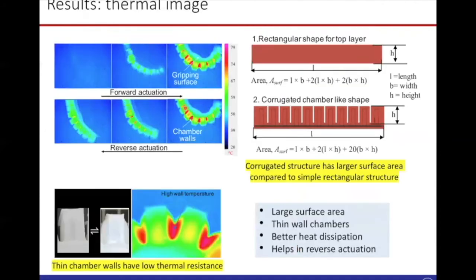Now let's look at the thermal image of this actuator in the forward actuation and in the reverse actuation. You can see in the forward actuation, the wall chamber comes to around 78 degrees Celsius, which is the boiling point of ethanol. If you want to reduce this wall temperature, one way is to use a liquid with a lower boiling point, for example, a liquid with 56 degrees Celsius. But on the gripper surface, you can see the temperature is around 45 to 50 degrees Celsius. You can reduce the temperature of this gripper surface by increasing the thickness of the skin on this side.